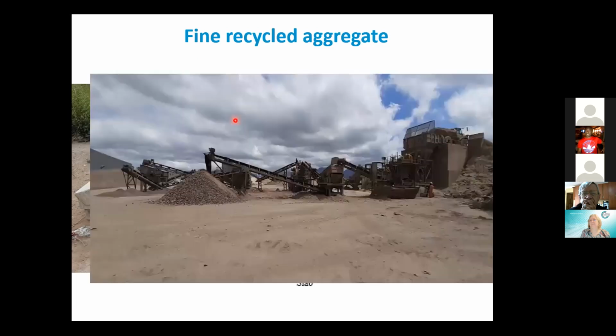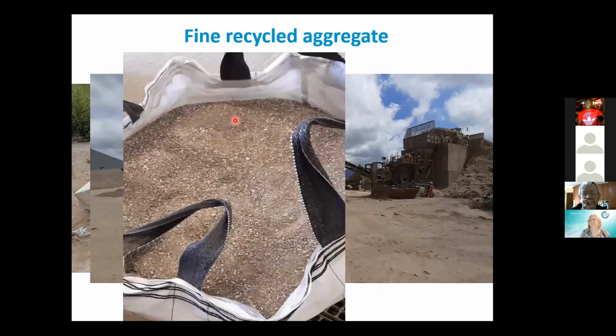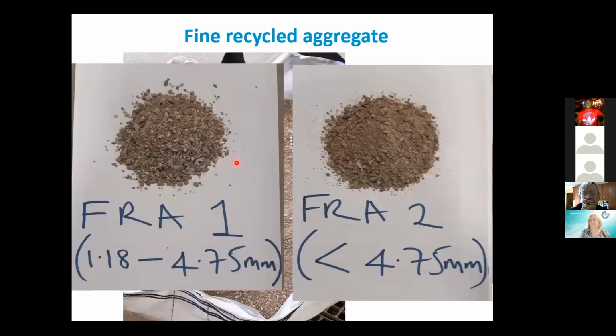Here is the crushing facility that was gracious enough to process our materials. This is CDL Services located in Philippi, here in Cape Town. Before crushing, the entire production line was cleaned to avoid contamination of my materials. This is what my materials look like after crushing. And of course, after sieving, these are the two fine recycled aggregate samples that were used.